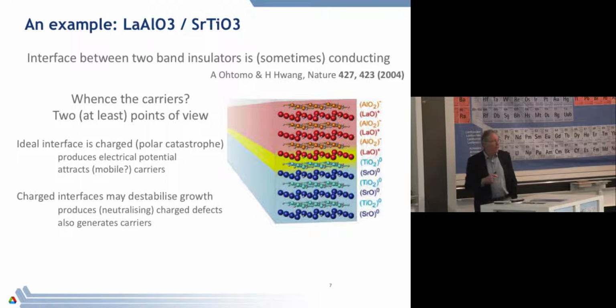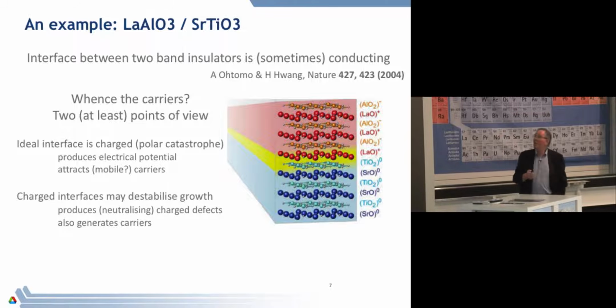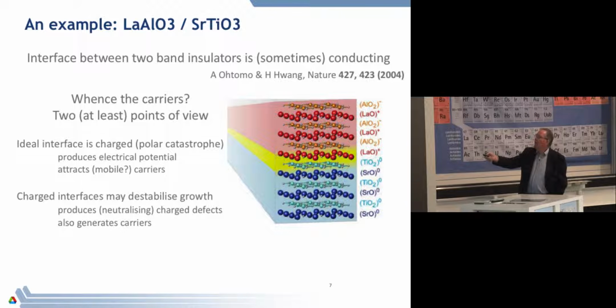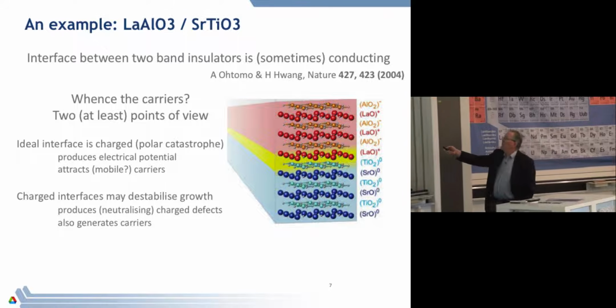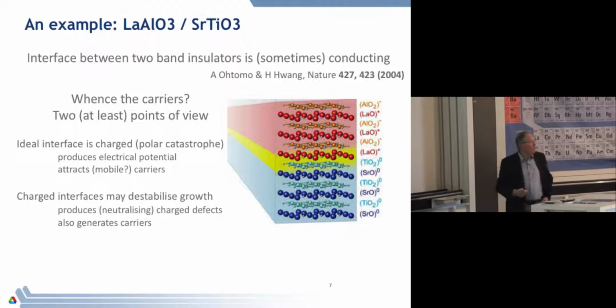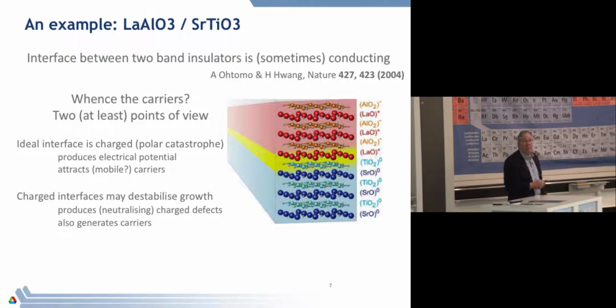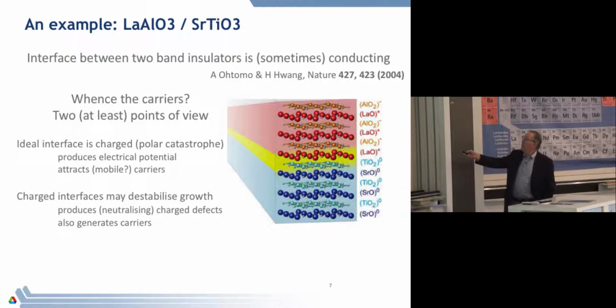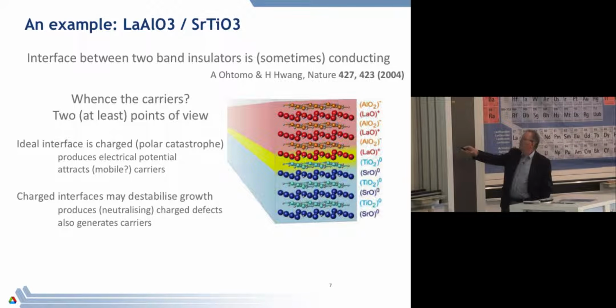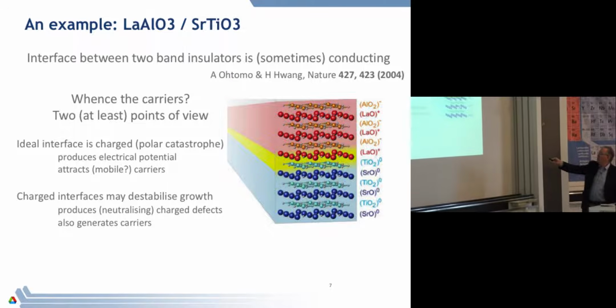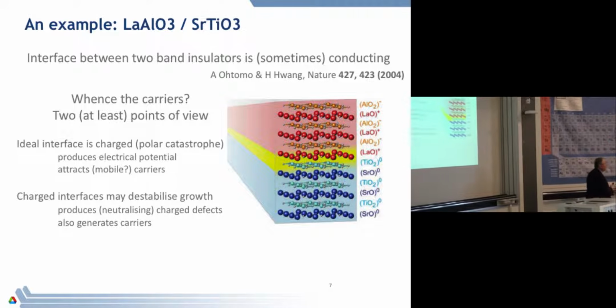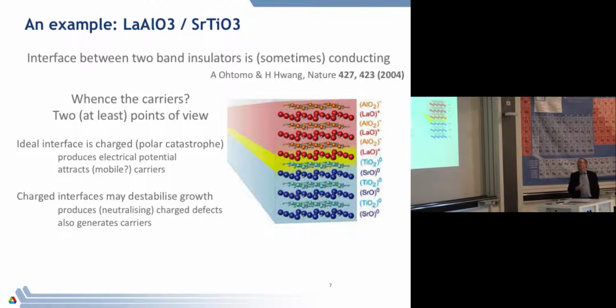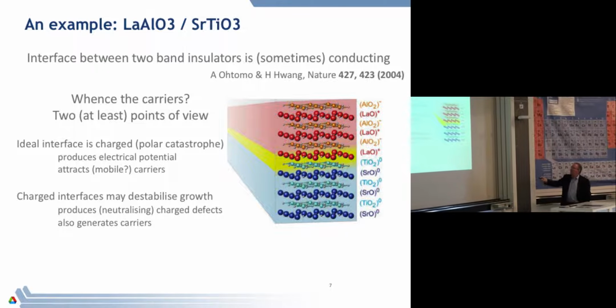Our colleague Jean-Marc Triscone and others have worked very heavily on this and done it. But if you take a perovskite material, which has now been simplified here to look at it in terms of these layers. So if you think about this, starting with strontium titanate from the bottom, and we're looking up in the 100 direction, the direction of those cubes, there's a layer of strontium oxide, then there's a layer of titanium dioxide, then strontium oxide. And if you just count the formal valences of this, each of these layers is actually neutral.